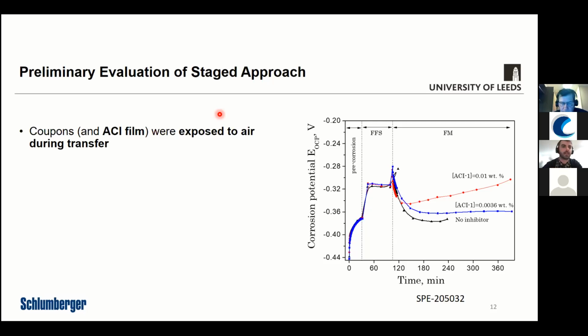Now that's quite important typically with corrosion inhibitors. When you have a film that's formed on the surface, if that's exposed to air, exposed to oxygen, it can sometimes fundamentally change the film that is formed on the surface, which introduces obviously some uncertainty in this particular test methodology.